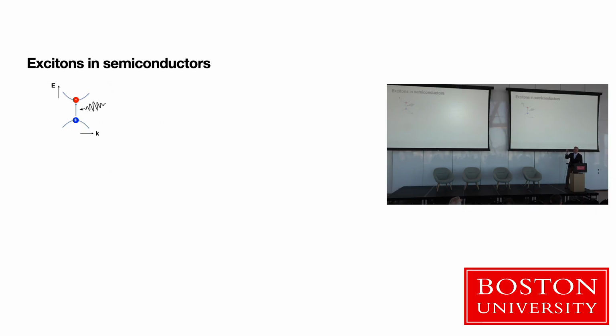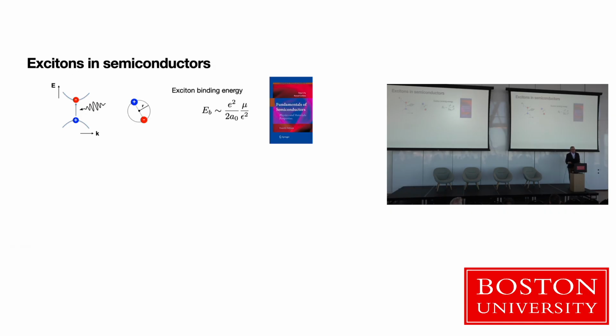So if you shine light on a material and it's got translation symmetry, and you can think about band gaps and valence and conduction bands, then you're essentially, in the classical theory, exciting an electron out of the valence band into the conduction band, and that leaves behind a hole, and they can interact. And that interaction in the simplest model would just be kind of hydrogenic.